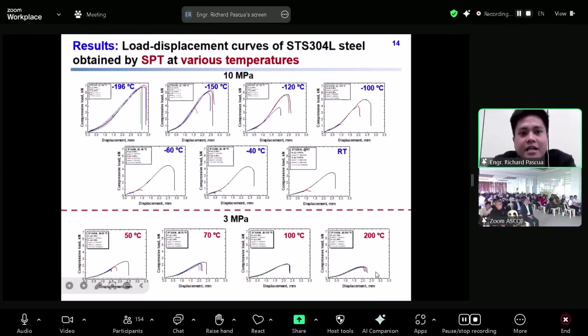As you can see, this is the load displacement curve obtained after SPT at various temperature conditions. When we lower the temperature from room temperature to negative 196 degrees Celsius, the maximum load, or the strength of the materials, increases under nitrogen environment due to the strain hardening at lower temperature. However, under hydrogen environment, severe hydrogen embrittlement was observed between room temperature and negative 60 degrees Celsius due to its low maximum load and fracture displacement at all punch velocity.